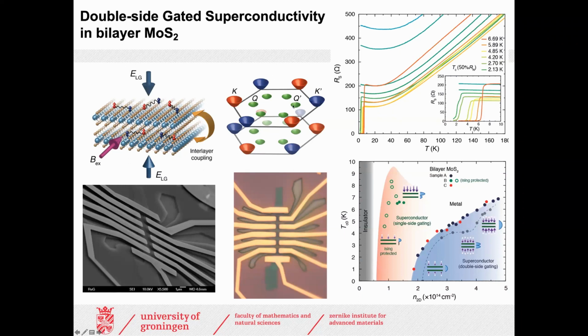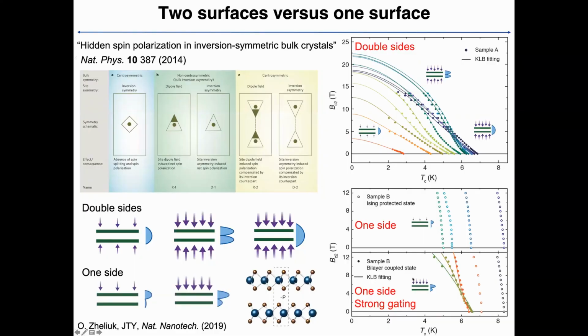So go to the band structure, not only the K point, we also have a Q point at the lower lying band for this bilayer system. So we have to fill all these points so that the carrier density requirement is much higher in this case. And then we go to the upper critical field. Remember, we have the system. If you make small gating, they are actually coupled with each other, and we are having a trivial system.